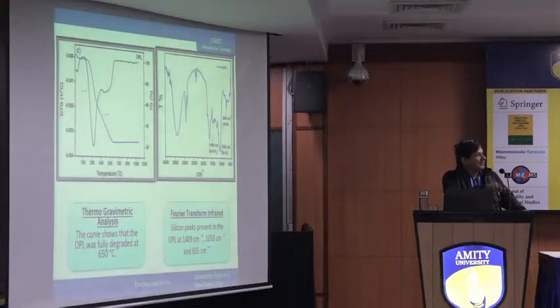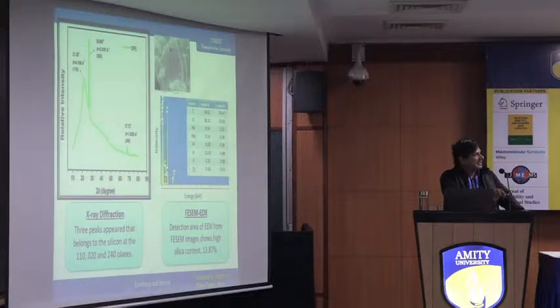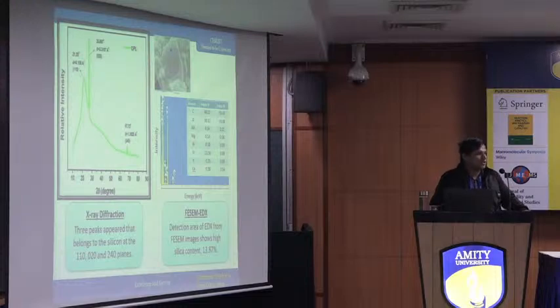Then you should know the FTIR. In the FTIR, you can see that all the natural agricultural crops contain this kind of feature, and at around 650 degrees you can see the degradation. So if you synthesize nanoparticle here, you are in the safe region. All the natural agricultural crops contain silicon peaks, so whenever you are working on bio-waste material, you have to make sure it gives the silicon peaks. Then XRD should also show the silicon peaks, like the 110, 020, 240 planes.